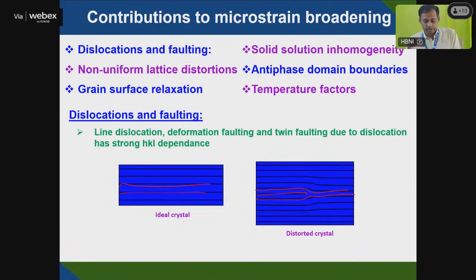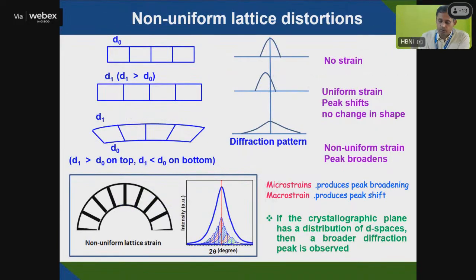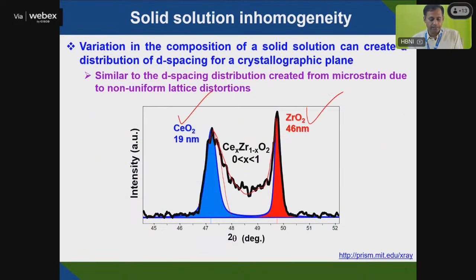If you have strain, you can calculate it. You can see this is D0, no strain, this is D spacing with no strain, and you are getting a highly symmetric peak. If there is uniform strain in one direction, like longitudinal, here D1 is greater than D0, elongated in one direction, and your peak is getting shifted. If it is both ways, both D1 and D2 are changing, top and down, and you are getting a diffraction spectrum that is broadened. So those types of information you get. Microstrain: in this strain there are multiple effects, and all those microstrain effects produce peak broadening, so that you can identify.